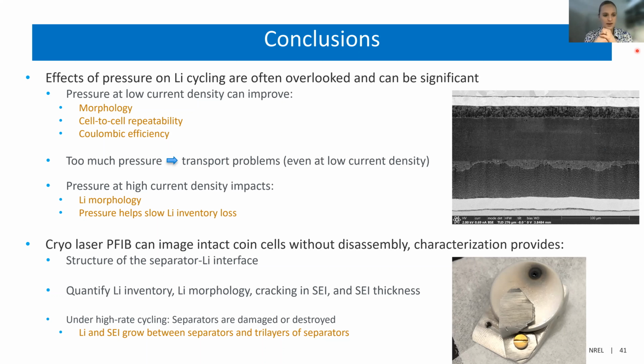And so we could use this technique to quantify the lithium inventory, the lithium morphology, cracking in the SEI layer, and also the SEI thickness within the cell. And we found that under high rate cycling, these separators are easily damaged and destroyed, and so they're not very compatible for lithium metal anodes, and that's an area of development.